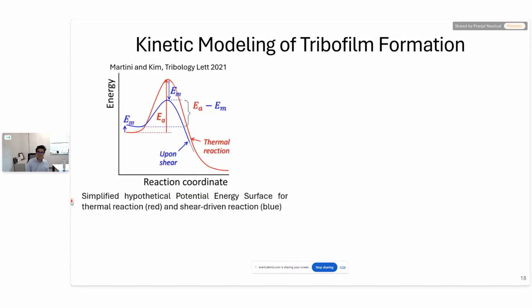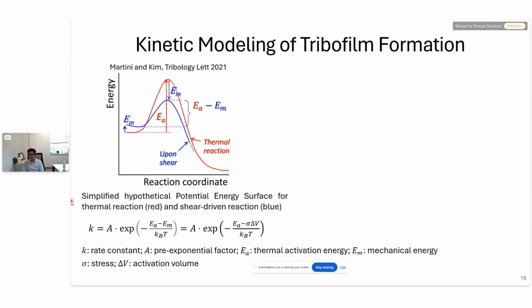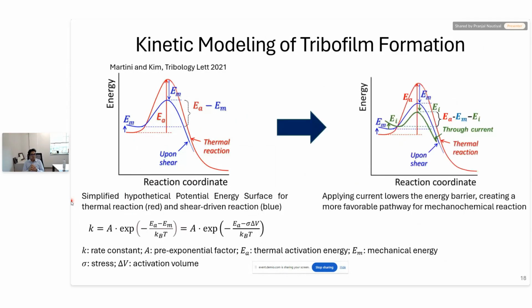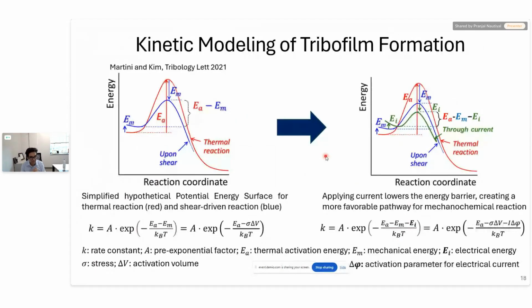Once again, I will go back to this important potential energy surface schematic I showed before. We have discussed this already, how mechanical energy plays an important role in mechanochemical reactions. They reduce the effective energy barrier for a chemical reaction to take place, and that's given by this Arrhenius-style equation. We propose to extend this framework to capture the effect of electric fields on mechanochemistry. So we propose that electric fields could further provide a reduction in energy barrier of mechanochemical reactions. This can happen either by a change in reaction pathway or by providing more energy to the reactants. And so we introduce a new parameter in the Arrhenius-style equation, EI, which captures the electrical energy supplied to the system.